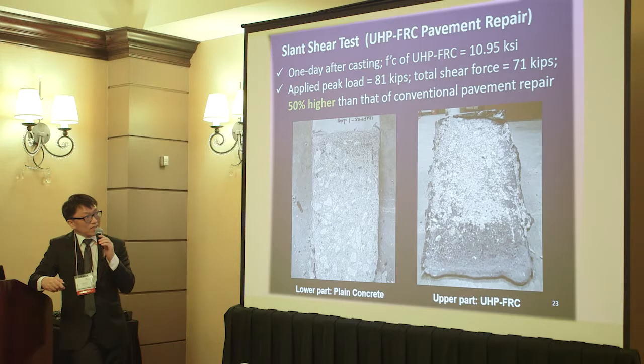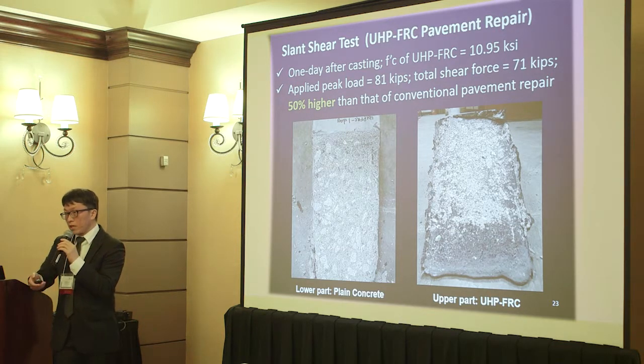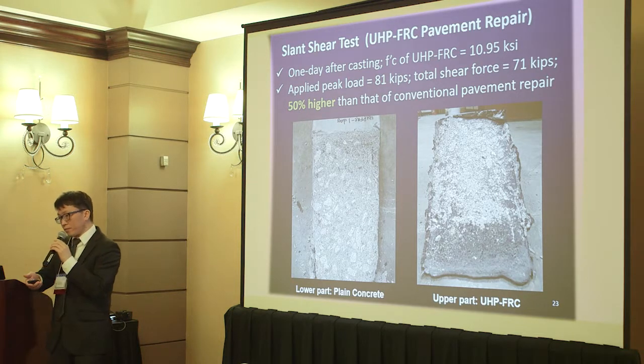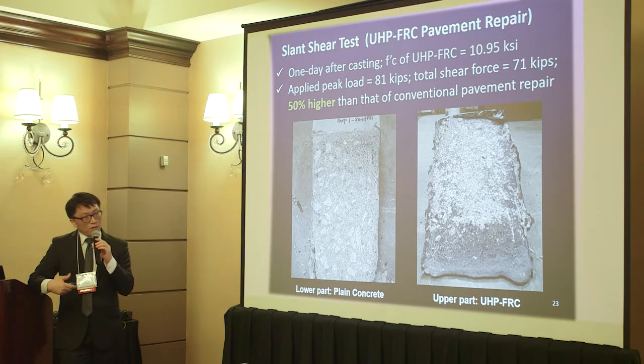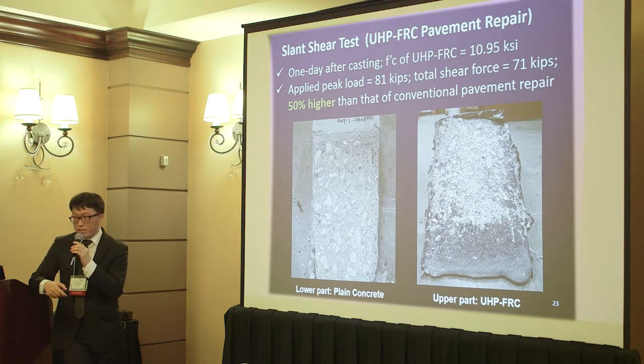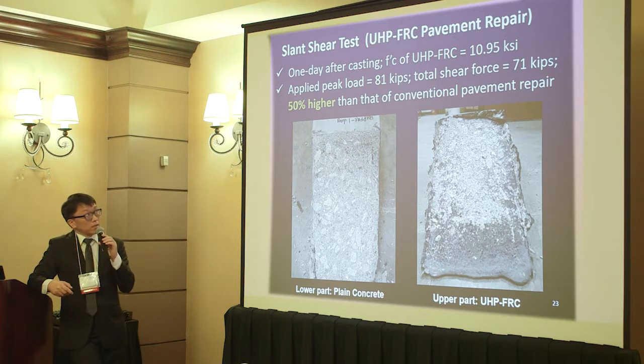Then the specimen does not fail until 81 kips. The previous one, conventional concrete with a dowel bar, failed at 55 kips. So this tells us that if we roughen the surface to some extent and provide a very strong repair concrete, it can provide even higher resistance to faulting or settlement. It's 50% higher. So in this case, we don't really need the dowel bar to provide resistance. All this roughening can be done before casting concrete, as I mentioned.